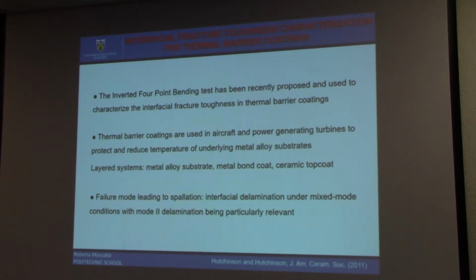And among the dominant failure modes is failure by spallation, which is driven by interfacial delamination. And interfacial delamination typically grows between the three layers and under mixed mode condition, and usually with a large component of mode 2.